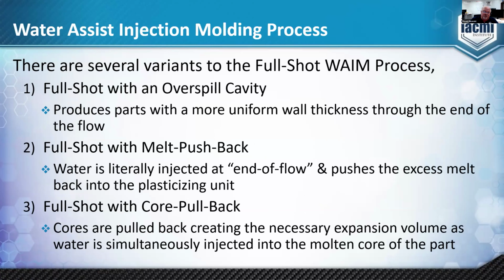There are several variants to the full shot water assist process. As you inject the water into the polymer melt, right, it's going to displace material from the core, and that material has to go somewhere. So in this case, there's an overspill cavity where the melt exits the actual part into an additional cavity, and that creates the volume for the water to fill.